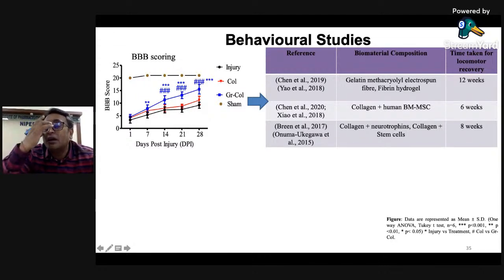We then compared the recovery rate with similar BBB scores reported by different researchers so far. We found a few reported materials, most showing recovery at either 8 weeks, 6 weeks, or 12 weeks. We achieved similar recovery in just 4 weeks.